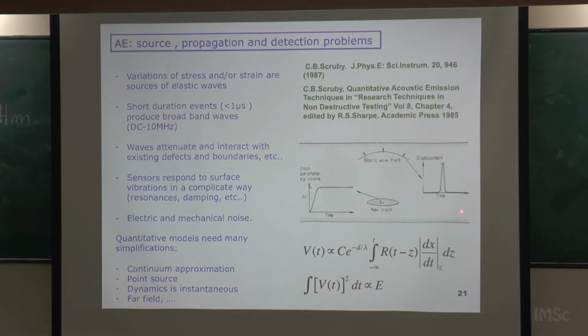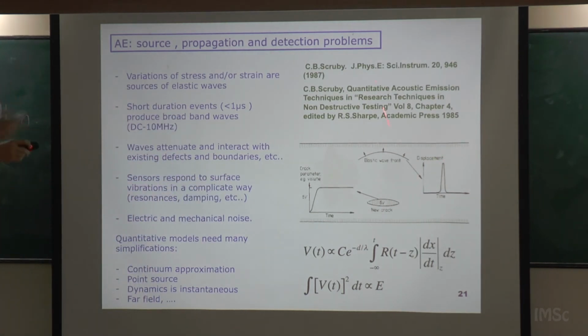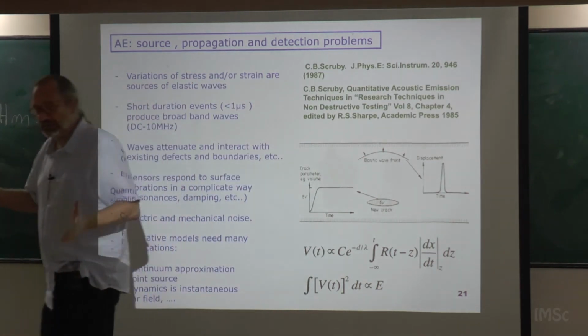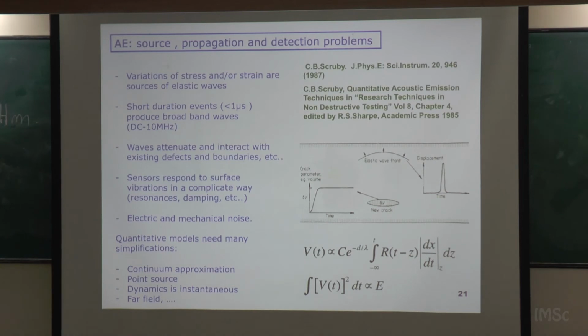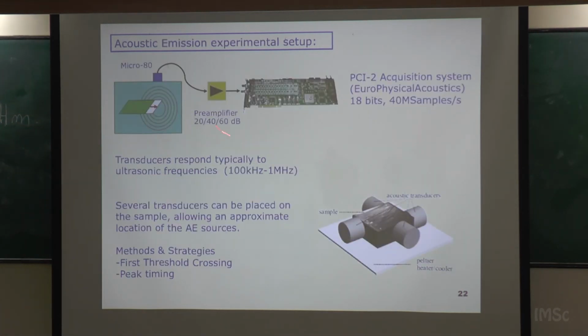It can be checked that integrating this function to the square power as a function of time, you can get an estimation of the energy. Okay, it's the energy that reaches your sensor, but that is a fraction of the energy that has been emitted somehow. This is the idea: detect the energy that is relaxed in this event. You remember that we go from one minimum to another, we win some free energy, the system relaxes, and proportional to this energy is what we will measure. Okay, this is how it works.